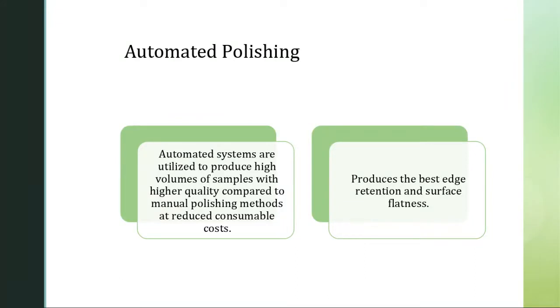It helps reduce your consumable costs, and it does produce the best edge retention and surface flatness, because when you're manually polishing samples, are you exactly putting that sample flat every single time when you lift it off to put it back on? Case in point: since these are fixed and you have a crosshead that drives the sample with force, they're always in the same position at all times. That's what produces your best edge retention.